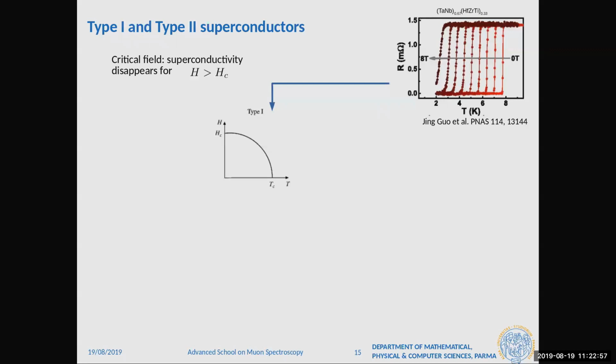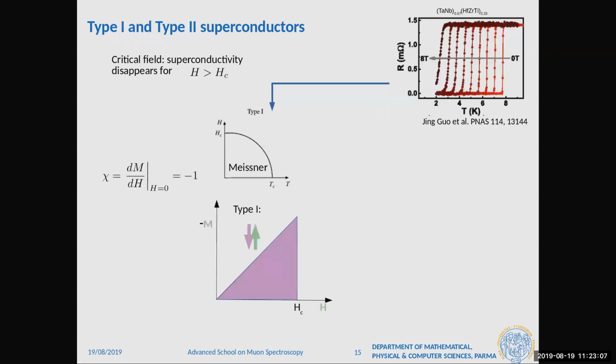And you have this curve, which is a phase diagram of the superconductor. This phase is superconducting, and outside here it's normal. But you can have other curves, and this corresponds to this kind of susceptibility, if you wish, that is dM/dH or M over H. I plot here M with a minus sign, so as I increase H, I have to increase minus M, until a point where it drops, which corresponds to the maximum field that I'm going up this way.